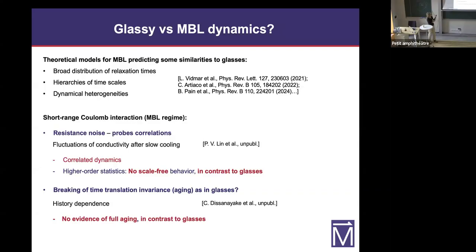So this was performed after cooling. So we do not change the density here. We did see some similarities to glassy dynamics, but when you look at, say, higher order statistics of the fluctuations, we do not find scale-free behavior that is characteristic of glasses, this hierarchical tree-like structure that I mentioned at the beginning of the talk.